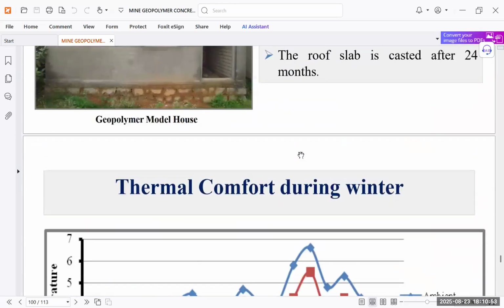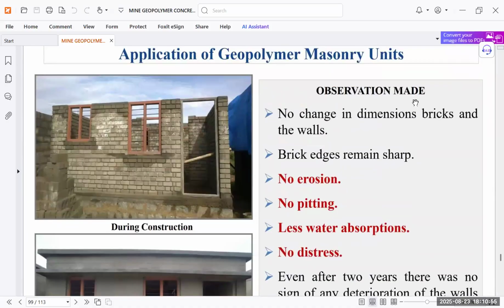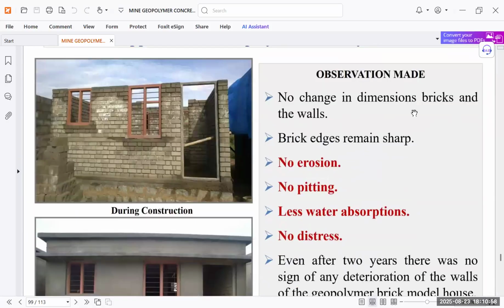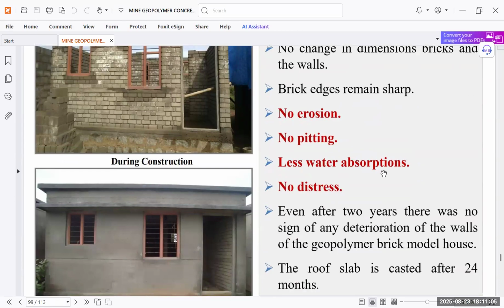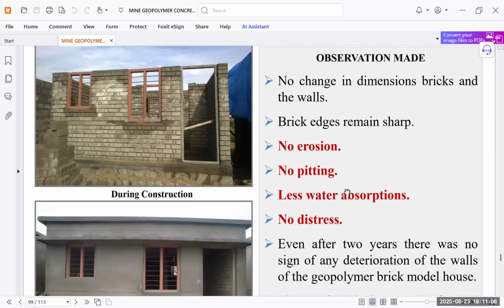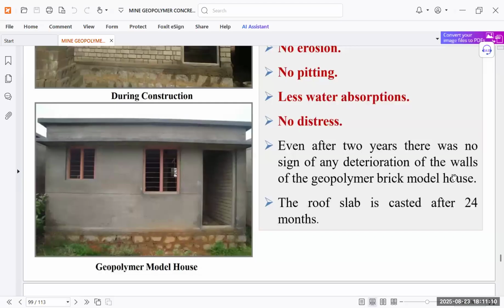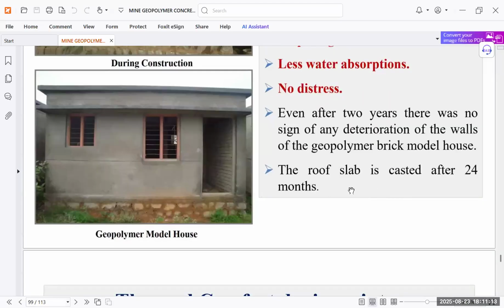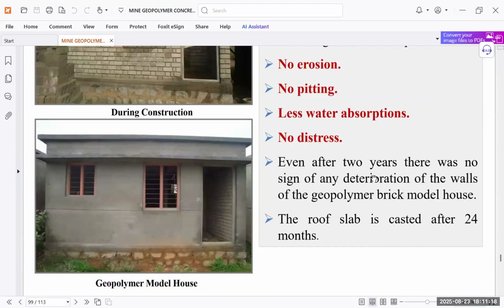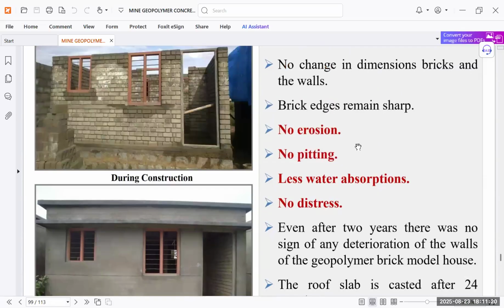After some observation made in geopolymer masonry, there is no change in dimension of bricks in the wall and brick edges also remained sharp, and there was no erosion, no pitting, and less water absorption, and there was no distress even after 2 years. There was no sign of any deterioration of the walls of the geopolymer brick model house. So the geopolymer brick model house has been tested, and the roof slab was also cast after 24 months. No erosion, no pitting, low water absorption, no distress using this geopolymer concrete. So means their practical applicability is very much taken care of.